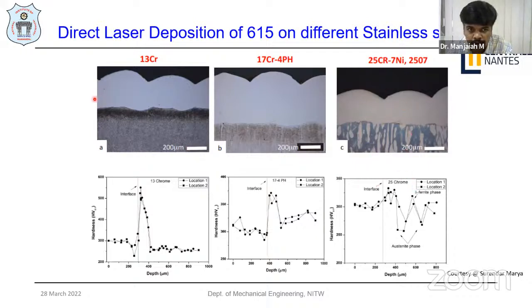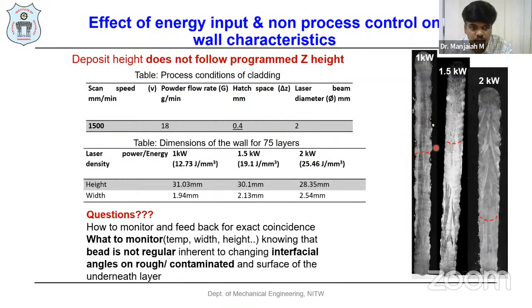In the transition zone, how the micro hardness properties as well as the grain orientations take place in the different repairing applications of the stainless steel materials. Even how we have to monitor to get back the feedback signals to coincide, how much temperature, how much width, and how much height of the layer has to be taking place if it is a very non-regular bead.